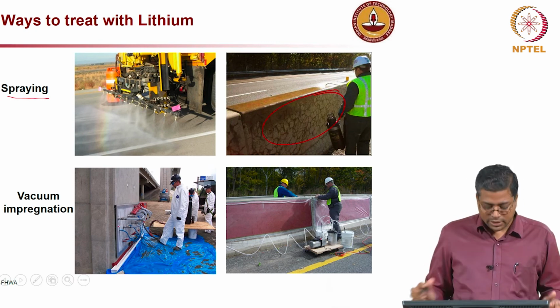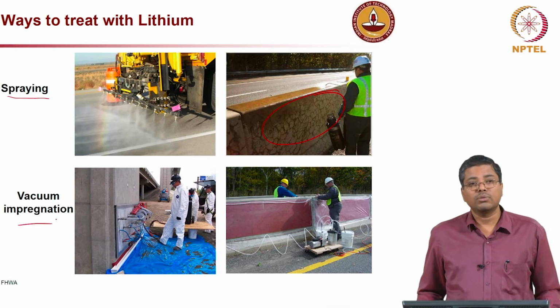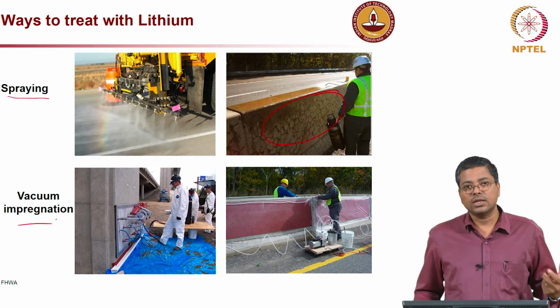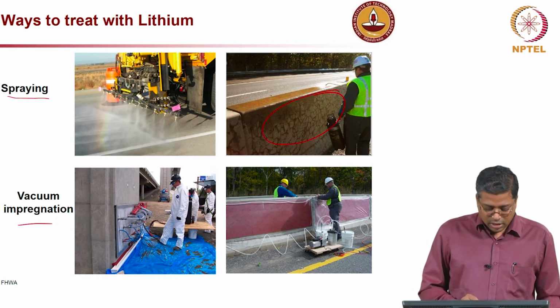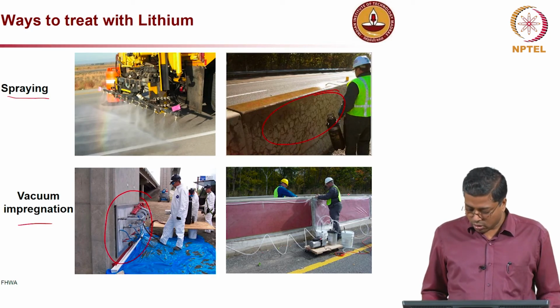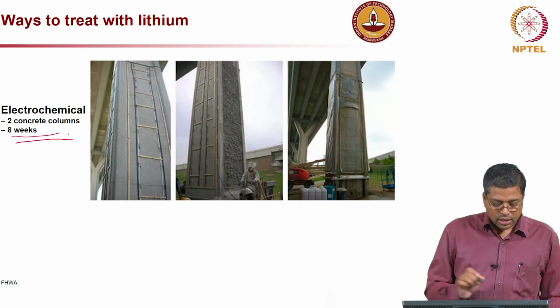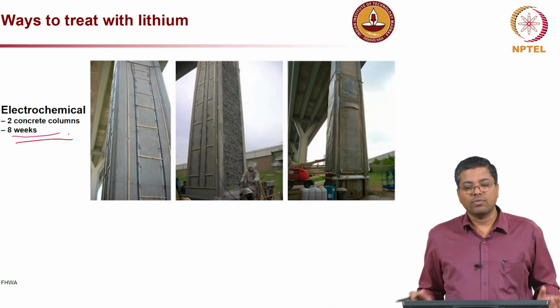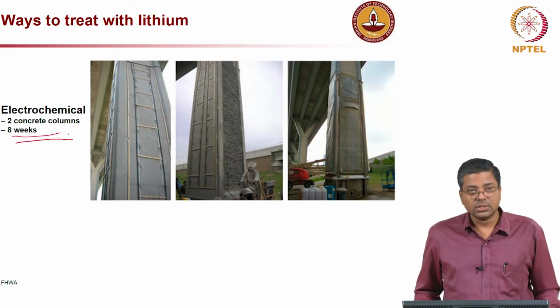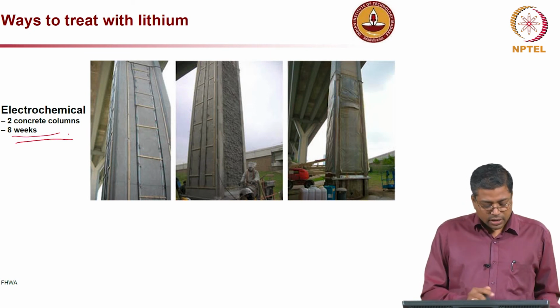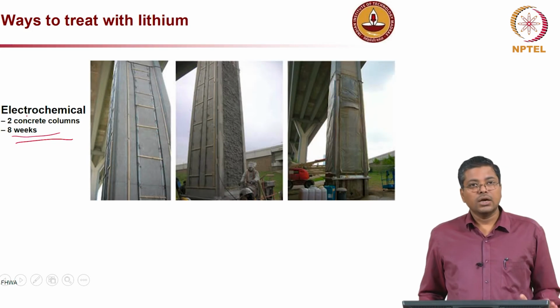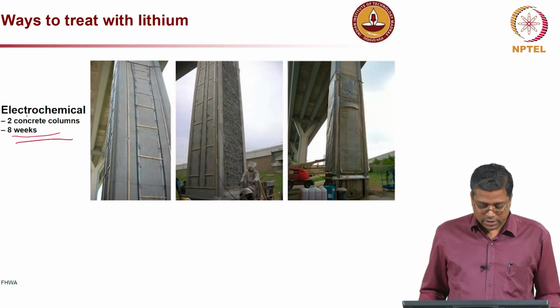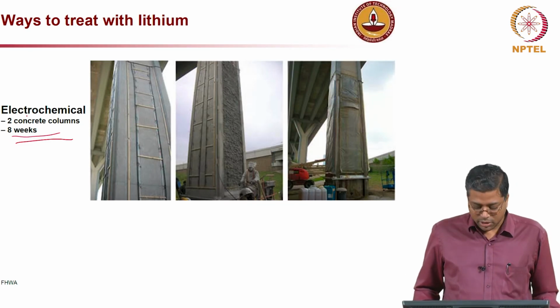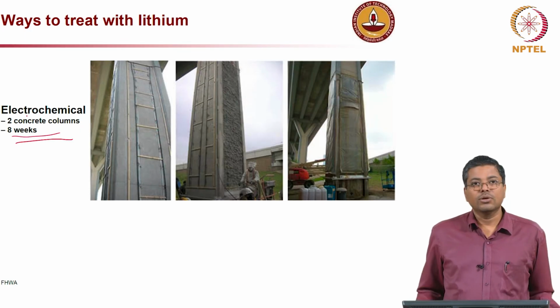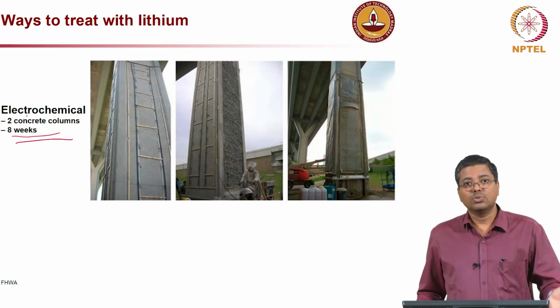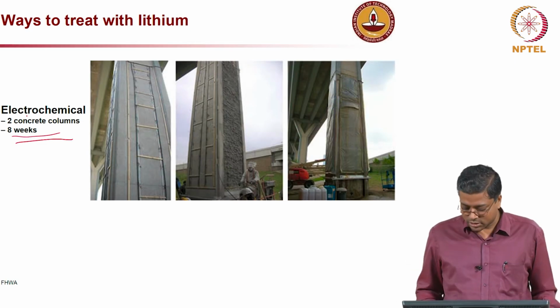Here in the first one you spray it, and the second over here is vacuum impregnation, where you create a vacuum pressure to suck the lithium solution into the concrete surface, but it is probably more expensive to do all this, it is not very easy. And there are also electrochemical methods where you apply a particular voltage which will drive the lithium ions into the concrete. But again, just look at this particular project, for 2 concrete columns it took almost 8 weeks to complete, to impregnate sufficient lithium into the concrete. So, it is expensive, but sometimes you might end up in situations where it is very important and you cannot really look at money, but at protecting the structure.